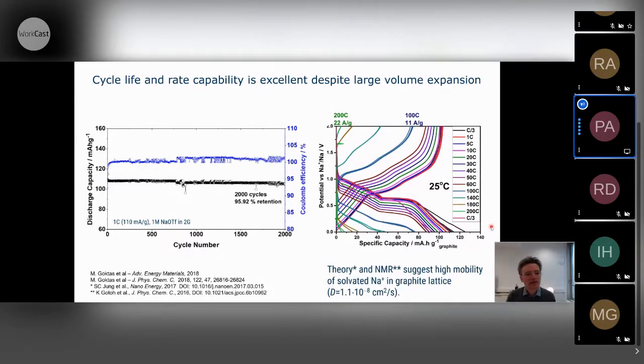One interesting thing about these solvated ions is that they can move very, very fast in graphite. Usually you would assume such large solvated ions are very slow because they are large and cannot really move in the graphite lattice. But the opposite is actually true. They move extremely fast, and the diffusion coefficient is higher compared to lithium ions diffusing in graphite. So there's a lot of mobility in this material, and therefore the rate capability is very high.